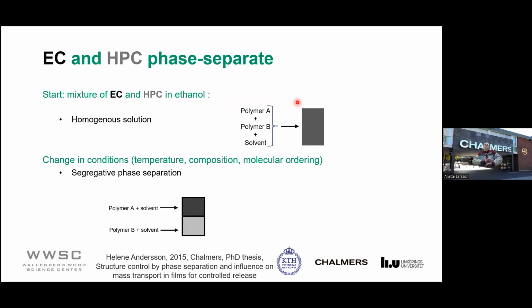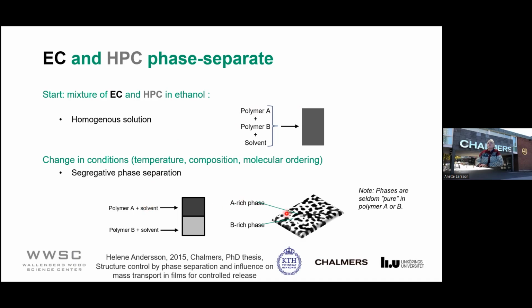So HPC and EC are polymers, and polymers, if you dissolve them in a solvent, are very prone to phase separate. You can have them in one phase in the beginning, but with time, if you change the temperature or the composition, then you will get phase separation. So you will get one A-rich phase, here illustrated by the dark, and one white B phase. And the B phase here is rich in B, but it still contains a little bit of A.